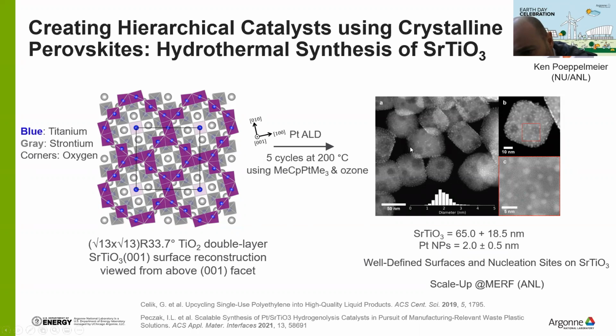These are very nice nanocuboids of strontium titanate. We deposit platinum using atomic layer deposition, because atomic layer deposition gives us the opportunity to control, for example, the particle size. And this white dot that you see on the surface of the strontium titanate is platinum. These are roughly 2 nanometer particle size. At Argonne, we have this facility called MERF, Materials Engineering Research Facility, that is a scale-up facility. So we can go from a lab scale of 100 milligrams to a kilogram scale of these materials.